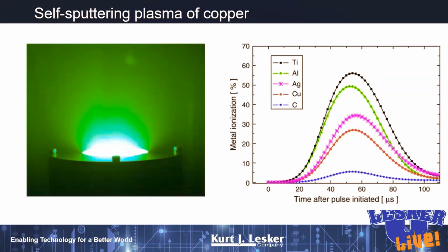If we look at metal ionization, again, this is a fairly old viewgraph, but lots of metals do it. Unfortunately, they have to be electrically conductive. HiPIMS has not been demonstrated with insulators, but you can see that things like titanium, aluminum, and copper have very high target ionization percentages. They're much higher than what you see with magnetron sputtering.